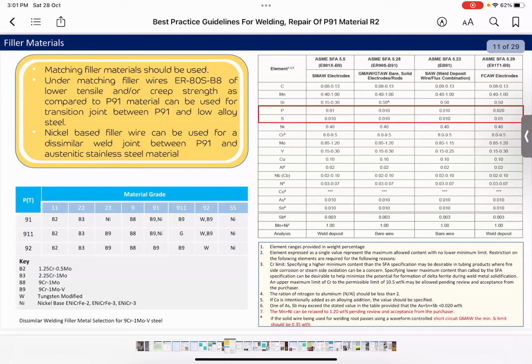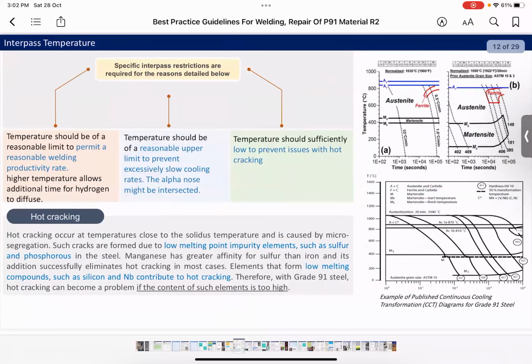This is a common issue, a common problem in GMAW short circuit, and it is addressed by ASME Section 9, where welders using this method must be qualified not only by NDT, but by mechanical test. The interpass temperature. The purpose of interpass is to permit a reasonable welding productivity rate, but the temperature should be of a reasonable upper limit to prevent excessively slow cooling.